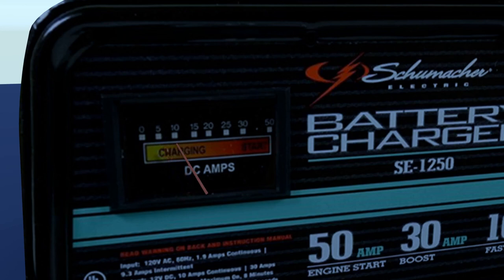The meter needle will immediately jump to around 8 to 10 amps. As metal dissolves into solution, and as the solution warms from the electrical charge, the amps will increase. Typical running amps are about 15, though you may find that your amps are somewhat higher or somewhat lower. At 15 amps, dissolving time is usually around 1 ounce per hour. After several hours, as the metal completes its dissolution, the amps will rapidly drop to zero, since there is no longer any metal to complete the electrical circuit.